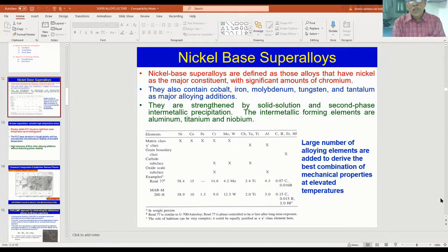They form the Ni3(Al,Ti) precipitate, which is coherent with the matrix. And there will be niobium and tantalum, which form Ni3Nb, Ni3(Nb,Ta), and this phase is known as gamma double prime.